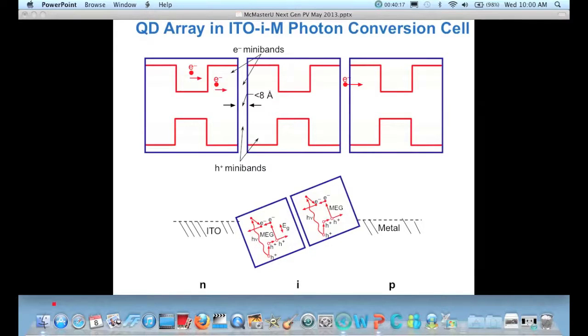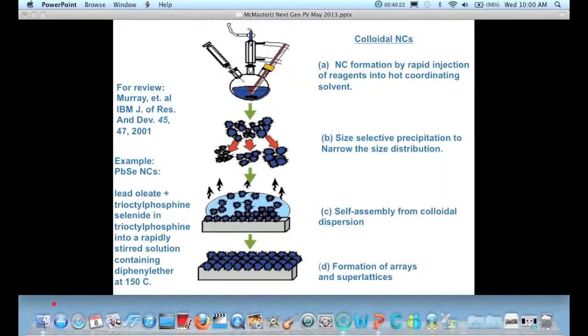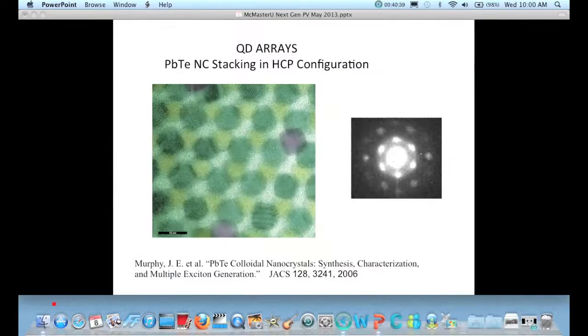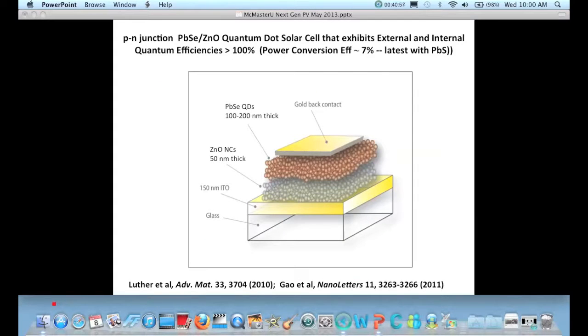It's something like a PIN structure, where the I region is an array of insulating quantum dots. And this can be made simply by first making the colloidal dispersions using simple chemistry, and then they self-assemble just by spraying or evaporating in a simple process to produce generally a disordered array. There are some regions which are ordered, but these are small regions of the structure where you have crystalline order, but on a macroscopic scale it's disordered. And if we make a solar cell simply by depositing, say, N-type zinc oxide quantum dots first, by evaporating a solution of zinc oxide nanocrystals with a second layer of lead selenide quantum dot nanocrystals, we get what we define as a nanocrystalline p-n junction.